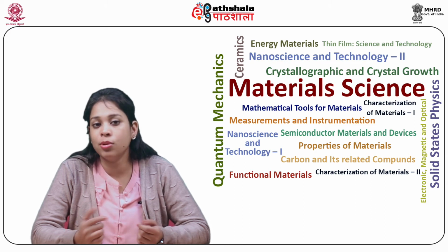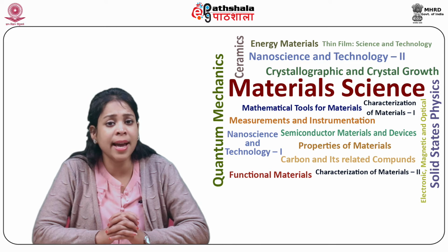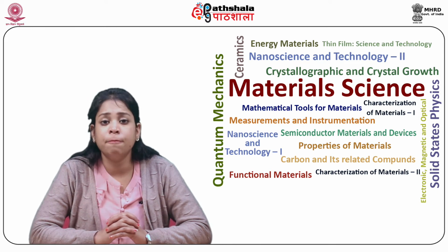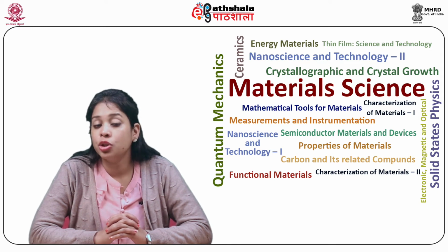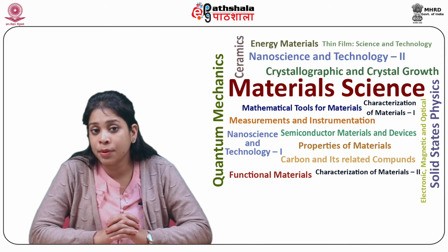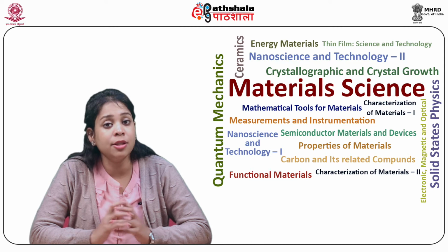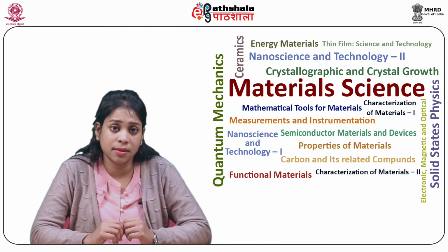However, the release of cadmium ions, that is Cd2+, could be reduced or eliminated by adding additional surface coatings. Scientists in Ireland have been using gelatin during the production of cadmium telluride quantum dots, thereby reducing the toxicity of the particles.